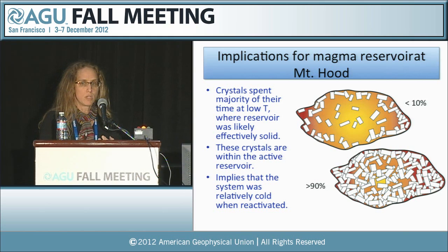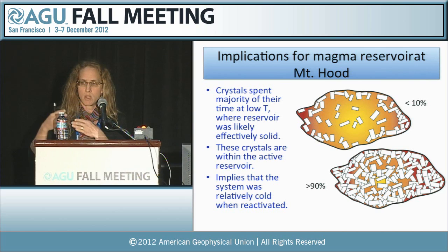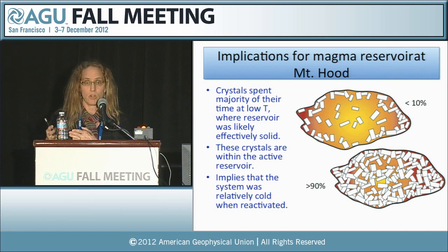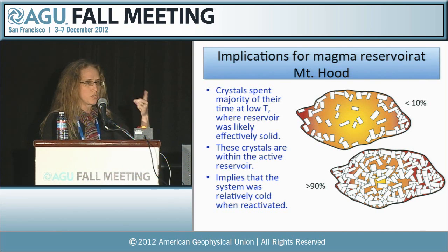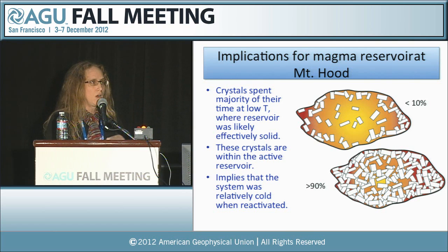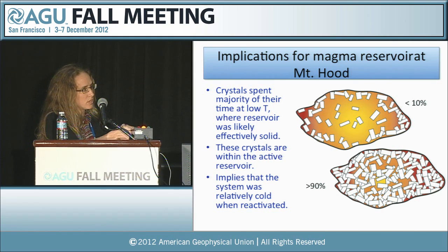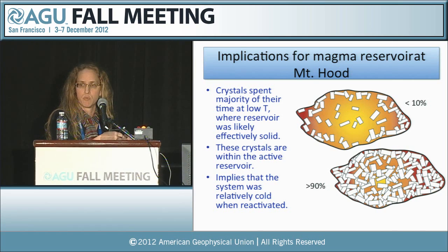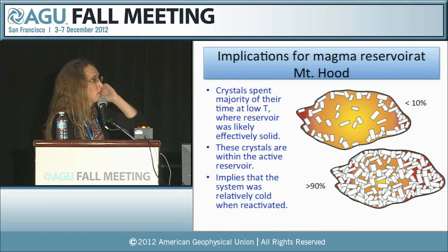And it's important to note that these crystals are present within the active part of the reservoir. These aren't just some sort of pod of magma that was intruded and then largely forgotten. The crystal size distributions are repeatable. The two most recent eruptions give us identical crystal populations, both in terms of the major and trace element composition and in terms of the crystal age. So it appears that this part of the reservoir is the part that is sampled over and over again as the silicic input for these Mount Hood magmas. And this also implies that the system was relatively cold each time that it was reactivated.